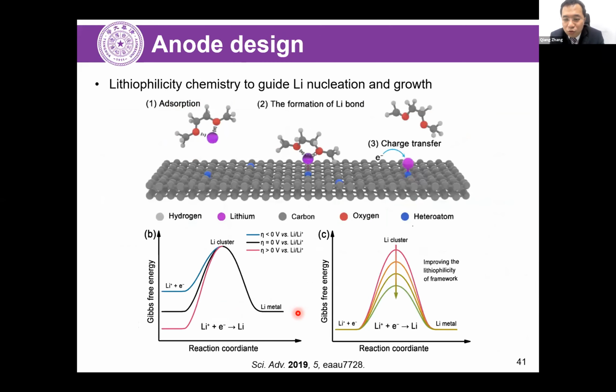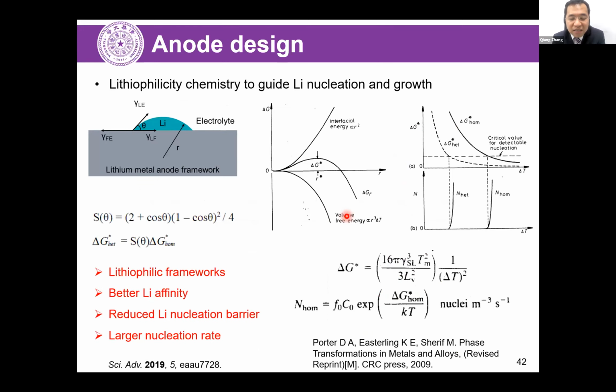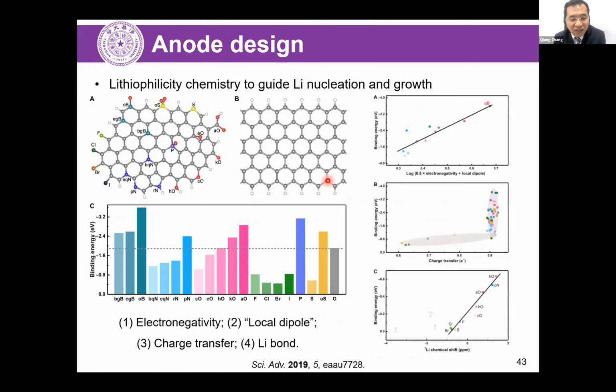So in this case, we try to regulate the interfacial reaction to protect the lithium metal anode by an inorganic-rich SEI. And also, if we want to build a full cell, we have to admit that a 30 micrometer lithium metal anode has too large a volume shrink or expansion for a working battery. So we introduce the addition of a host, and it is found that the host not only provides space for volume expansion or shrink, but also provides lithiophilic sites which prefer to bind the lithium ion by lithium bonds, with strong binding energy.